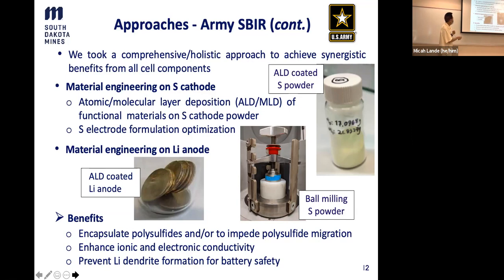And then the other one is the lithium anode, where it's sort of material engineering. So we ALD coat the lithium. So this is actually coated. You see it's not silver or shiny. It's kind of this color. So why do we do that? The purpose is that we try to encapsulate the polysulfide with the coating and impede polysulfide migration, so the shuttle doesn't happen, enhance the ionic and electronic conductivity, and then the last one is to prevent lithium dendrite formation. So those are the intended benefits.